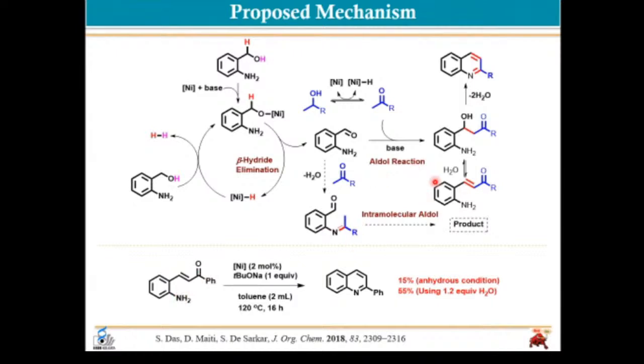But once we have water, what will happen? This water will undergo an oxo-Michael addition with an OH here, and once it becomes a single bond after Michael addition, this becomes flexible and the bond can rotate easily. If it rotates, then this ketone will come close to this amine and can condense easily, giving the quinoline product. That's why in the presence of a little bit of water, the reaction efficiency is much higher. Just by doing this control experiment, now we are sure that this reaction goes via first carbon-carbon and then carbon-nitrogen bond formation, not via the other pathway.